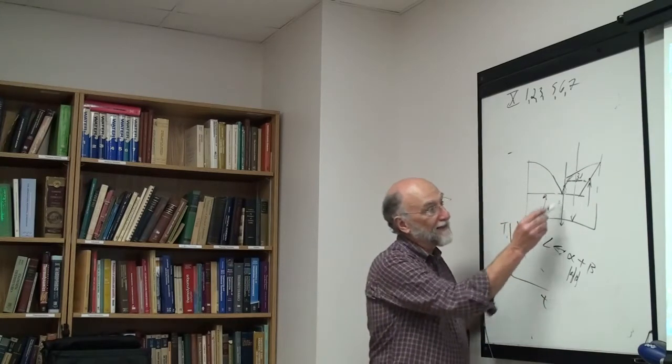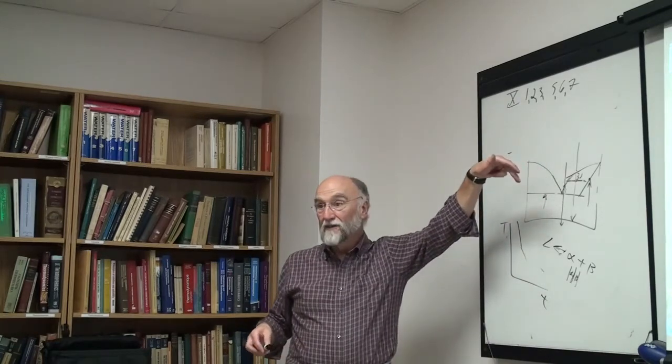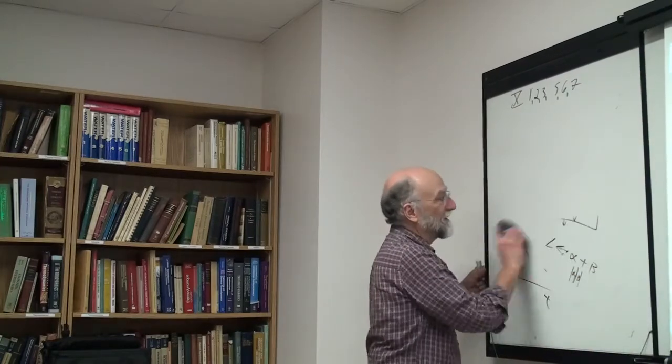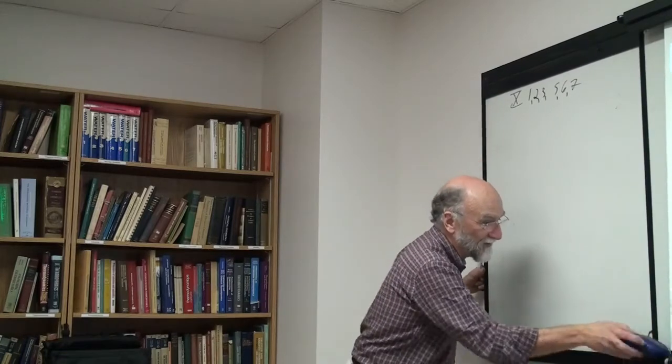Okay, so you're not going to get an awful lot of, there's a kinetic restriction here. It doesn't suddenly all melt. It melts at the boundaries, so cooling curves are better, I think, for liquiduses and eutectic. Heating curves are going to be better for solidus. This now brings us to differential thermal analysis.